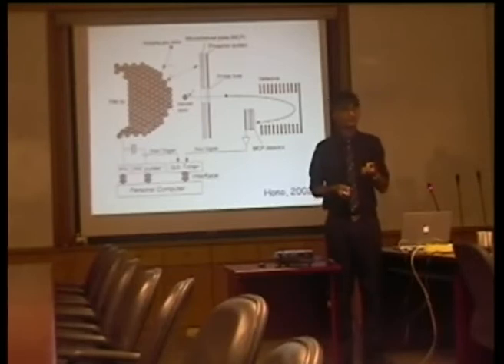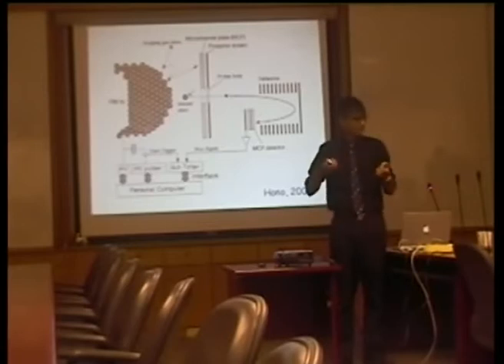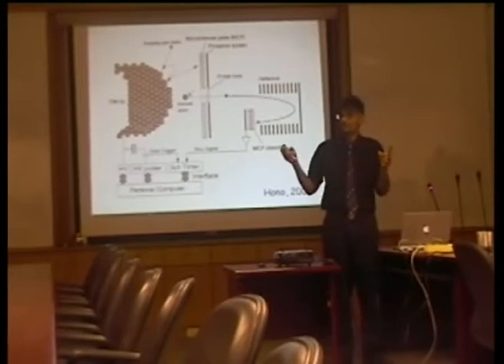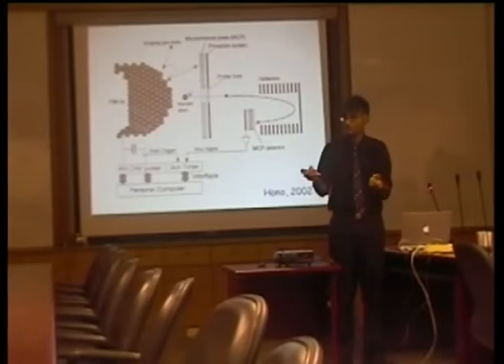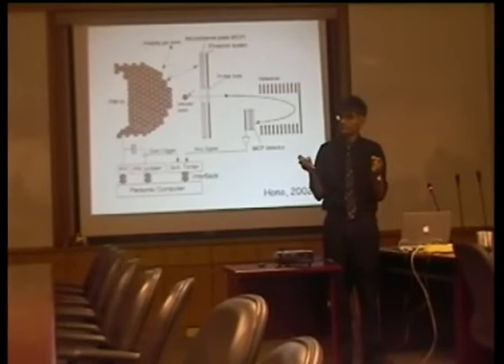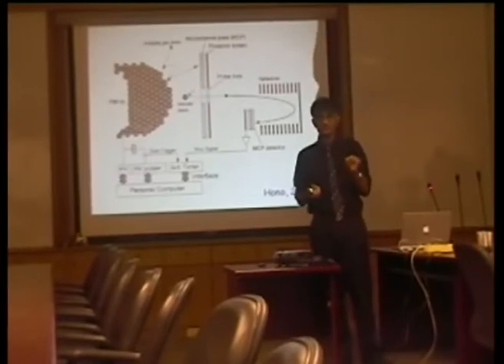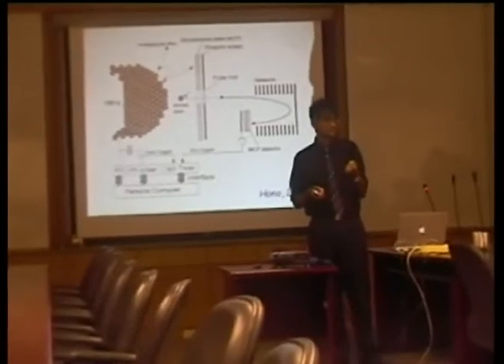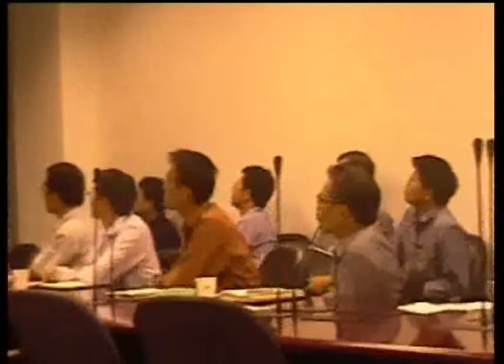But the second characteristic of this is that when you pull out the atoms from the specimen by applying an electrical pulse, you can measure how long they take to fly between two points. And from that, you can say, okay, this is carbon, or this is hydrogen, this is iron. So this is time of flight mass spectroscopy. So you not only have atomic resolution, you can see atoms, but you can also chemically analyze individual atoms. Okay? So this is a field ion microscope atom probe. And when you look at that steel wire, which has been strained to a true strain of 9, it looks like this. A single dot there is one atom.